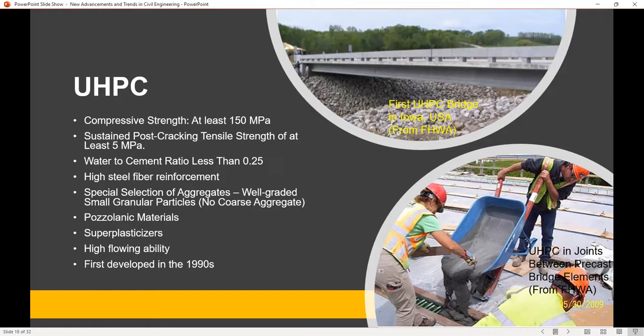So this will address that. Of course, you will use steel reinforcement in UHPC as well to provide additional strength. Now, one thing typically with UHPC, water to cement ratio is less than 0.25. If you have worked with concrete, you usually work with higher numbers. So this will make it very difficult to work with. That's why you have to use chemicals, specifically super plasticizers, to make it flowable so you can place it correctly.